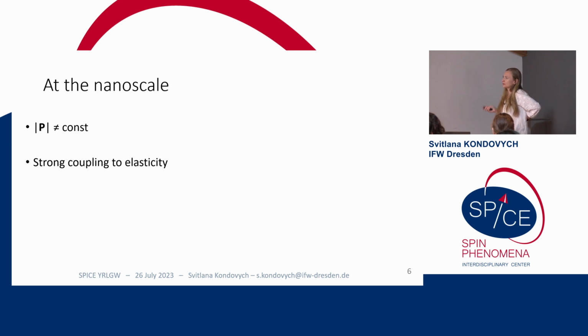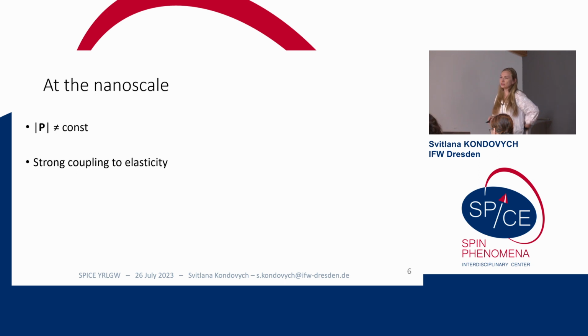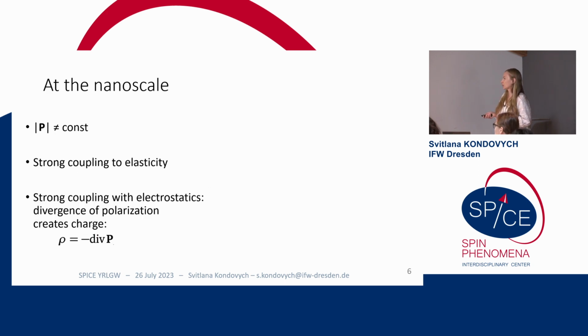I will repeat that the polarization is strongly coupled to elasticity, to the mechanical degrees of freedom, which is a rare situation for ferromagnets. Usually the magnetostriction in ferromagnets is low and neglected. It's different for antiferromagnets, but for ferroelectrics, strain is one of the important tuning parameters, so there is this large coupling, and large coupling with electrostatics.